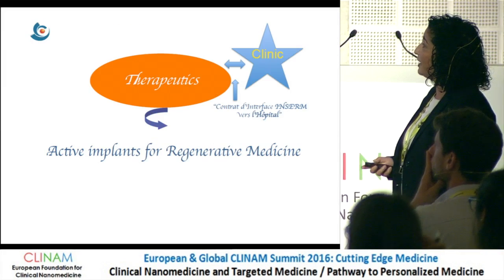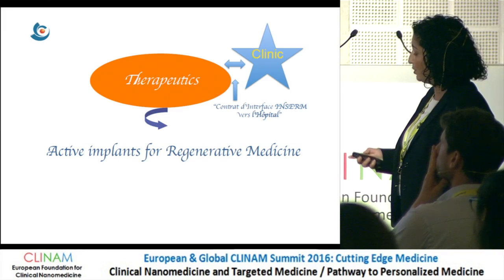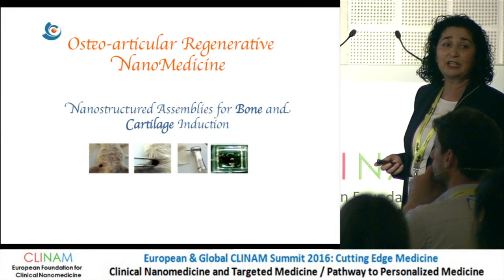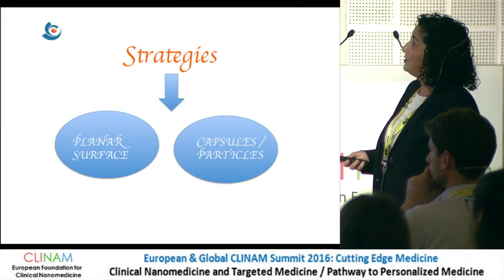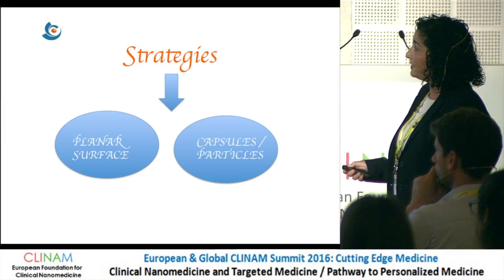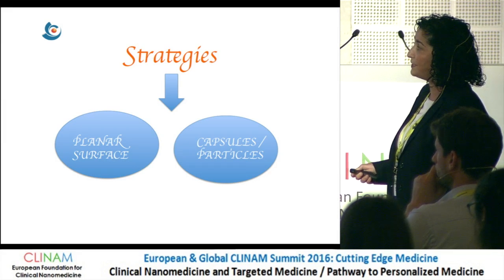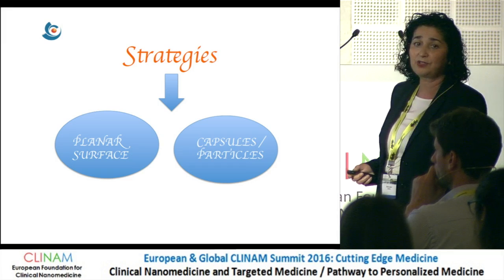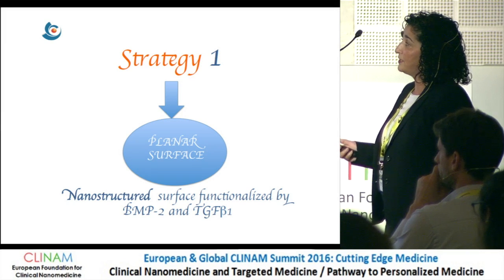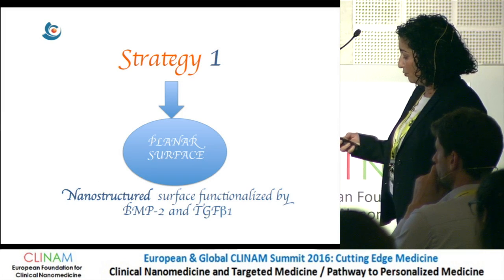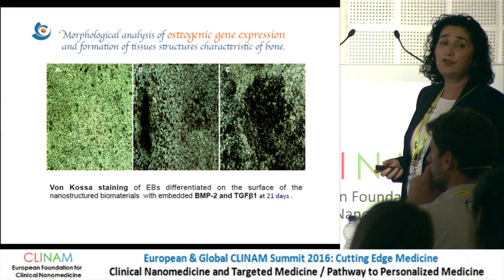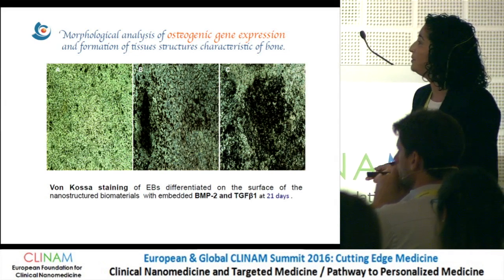For smart nanostructured implants with interaction with the clinic, we developed active implants for regenerative medicine for bone and cartilage regeneration. We did two strategies: planar surfaces like a membrane we can implant, or capsules and particles we can inject. We applied this nanoreservoir technology on the surface of the planar implant by incorporation of bone morphogenetic protein 2 (BMP2) or TGF-beta 1.